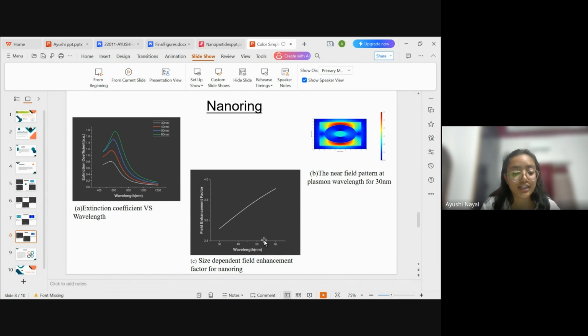The first graph is between the extinction coefficient versus the wavelength. As you can see, the value of extinction coefficient increases with the increase in size of the particle. It is because the value of extinction coefficient increases with the increase in size, which indicates the enhancing light matter interaction. The B graph is for the near field pattern at plasmon wavelength for a 30 nanometer nanoring structure. And then the C part is the size dependent field enhancement factor. The graph shows a linear increase for the field enhancement factor. It increases linearly with the increase in size.